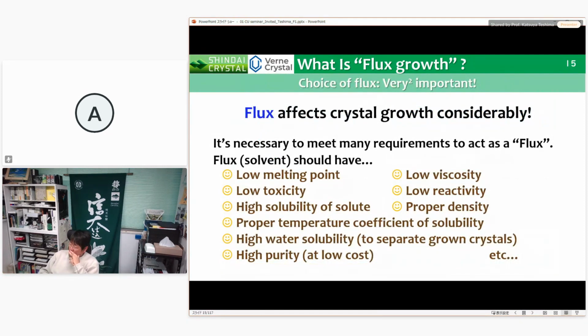For flux growth, the choice of flux is very, very important because flux affects crystal growth considerably. It's necessary to meet many requirements to act as a flux. The flux should have low melting point, low viscosity, low toxicity, low reactivity, and so on.